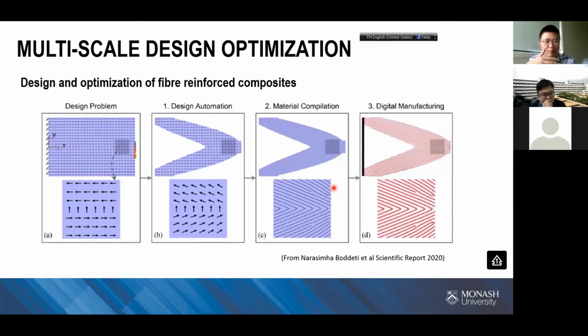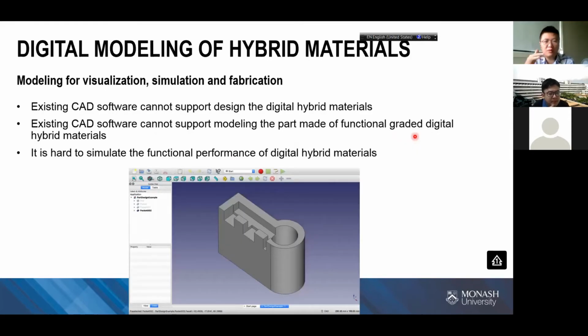My research is not only focused on lattice structures. We are also working on composites, continuous fiber reinforced composites. This is a collaboration project I did when I was a postdoc researcher at SUTD with Professor Narasimha, who is now a professor at Washington State University. We are working on designing and optimizing the fiber orientation inside the part and optimizing the micro shape. You see the shape of the part changes, and the fiber orientation also changes. We use an algorithm to link those short fibers into continuous fiber. Finally, additive manufacturing, using 3D printing techniques, fabricates this type of composite structure, which has the fibers oriented to the principal stress directions. So those are about optimization.